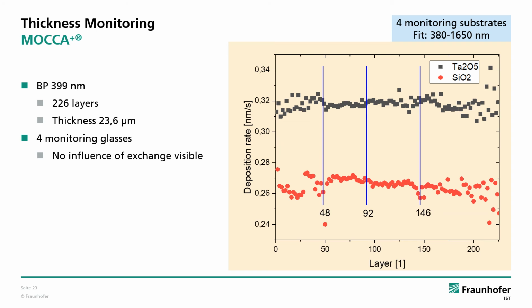The calculated deposition rate remains very constant. At the beginning, the machine was brought to the temperature region where it saturates during the process. Thus, you do not see any changes at the batch start. Also, the exchange of the substrates without an additional heating phase does not lead to another detected deposition rate.